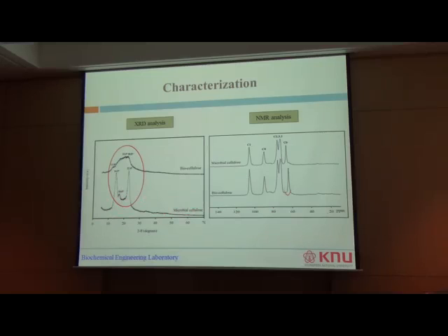So these results were further confirmed through the NMR analysis. We can see that all 6 carbons were present in both types of cellulose, but the position of carbon 6 was shifted toward the lower ppm. That showed the structure of cellulose 2. So both XRD and NMR analysis concluded that the cellulose produced by the cell-free enzyme system was actually of cellulose 2 polymorphic structure.